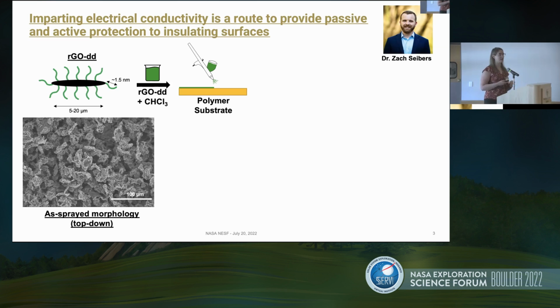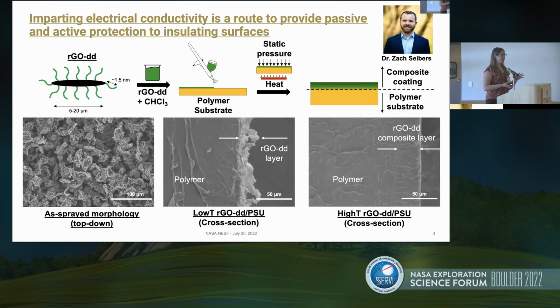So this makes a fairly thick, disordered, very porous nanocomposite coating. We then take this entire assembly and we apply a static pressure and heat, and this allows the polymer substrate to actually infiltrate that sprayed coating to make a surface localized electrically conductive nanocomposite structure at a much higher loading than we would be able to get from a melt blending type approach.